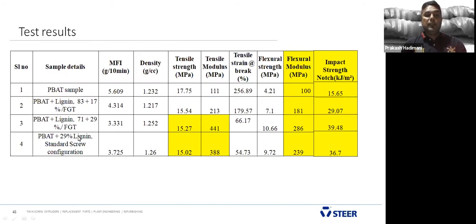And for the FGT technology, we compared both the FGT and the standard technology. FGT is giving a higher impact strength and flexural modulus compared to the standard. FGT is giving better mechanical properties compared to the standard technology. Even if you see the tensile strength, we are getting 15.27 in the FGT technology, but slightly reduced in standard. Tensile modulus is similar. FGT is giving better tensile modulus, and tensile at break is also higher with FGT, lower in standard technology.